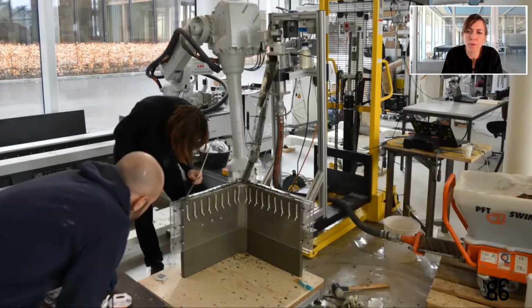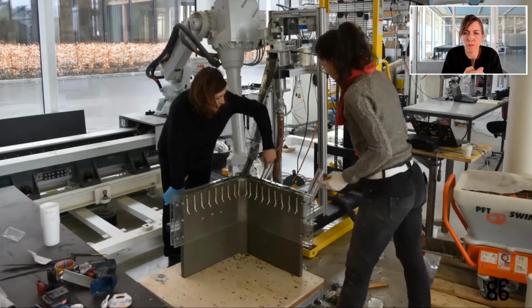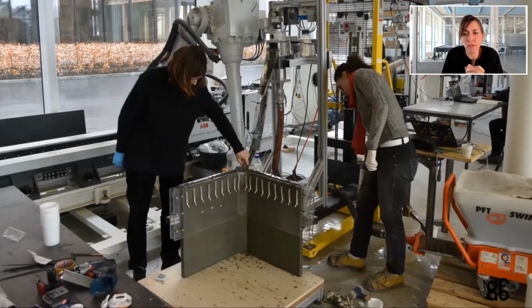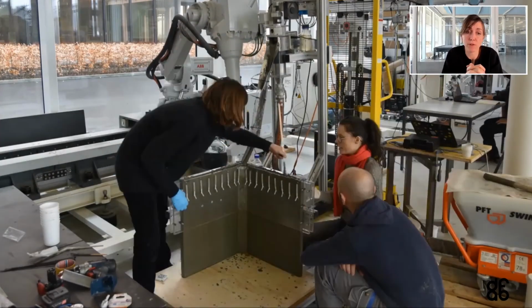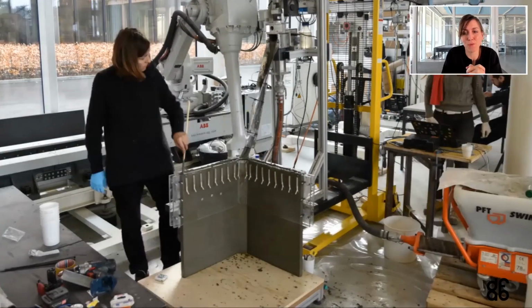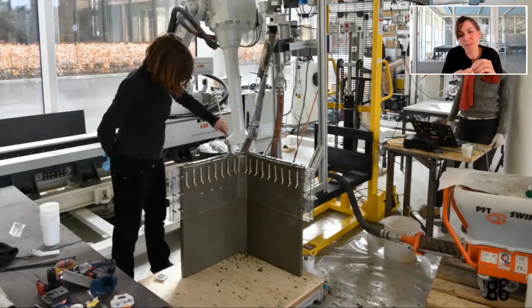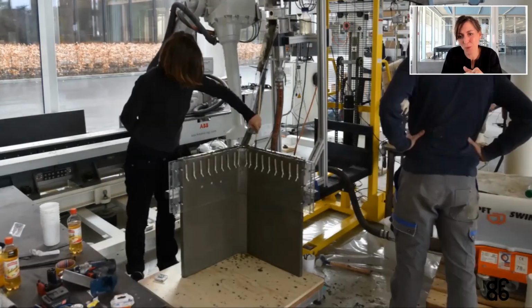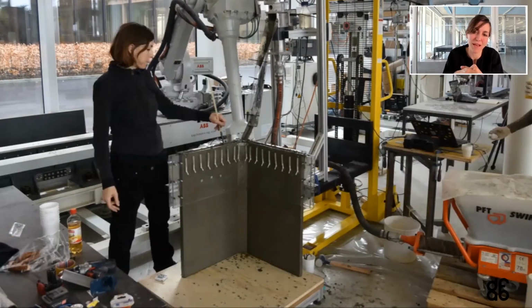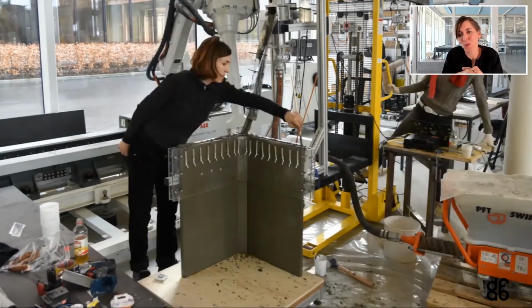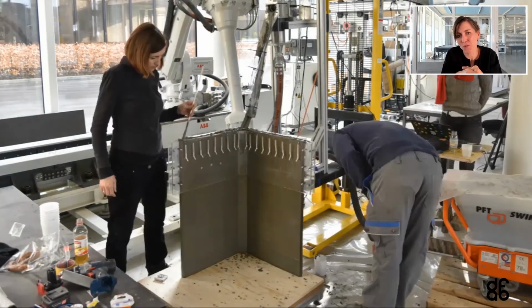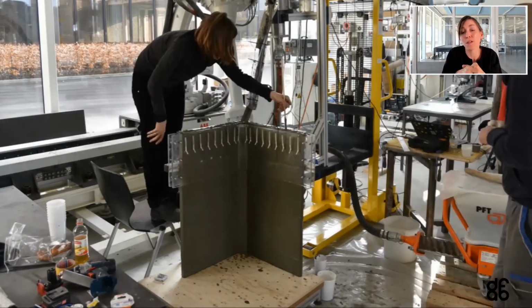After numerous experiments and material adjustments, it was possible to produce a set of thin folded elements. However, it was necessary to manually distribute the material, and the design space was rather limited, both in the possible shaping and in the height. So this was mainly due to the slow hydration of the material, which Anna Szabo can tell you much more about.